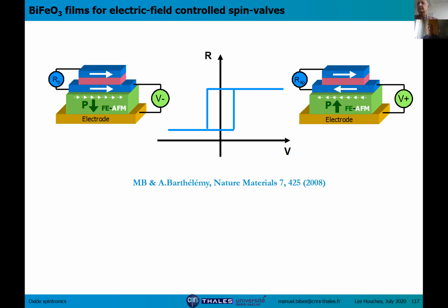So if the electrode is not too thick, you are still able to probe the deformation of the ferroelectric below the electrode through its piezoelectric effect. So the electric field is applied globally across the whole junction area, but you still have a spatial resolution because you are probing the deformation, basically the piezo response, at the local scale. So if the top electrode is only maybe 10 nanometers thick, or 20 nanometers thick maximum, you are able to measure contrast below it.